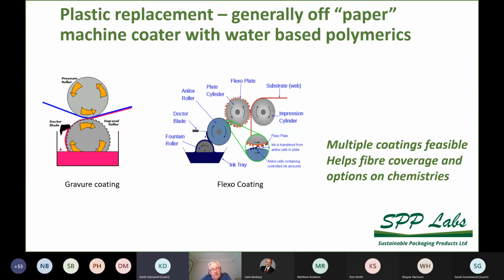Similarly, flexo is another process being used to coat papers and boards with barrier coatings. In a way, this is similar to the gravure. You have a pickup roll transfer into an anilox roll, which is a roll with cells, and that transfers to a transfer roll, which transfers to the paper. But the flexo press offers, again, multi-layer coating essentially in one machine. Flexo press coating that I'm utilizing today has a central impression cylinder with 8 coating units, and then has additional separate overprint units. So we can, in theory, apply up to 9 coatings.